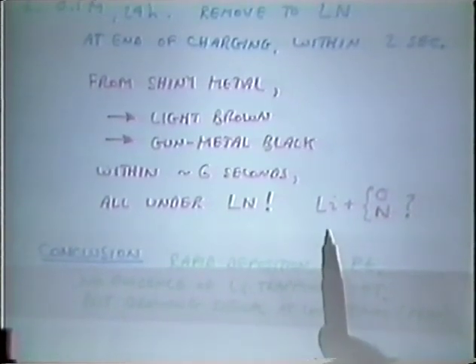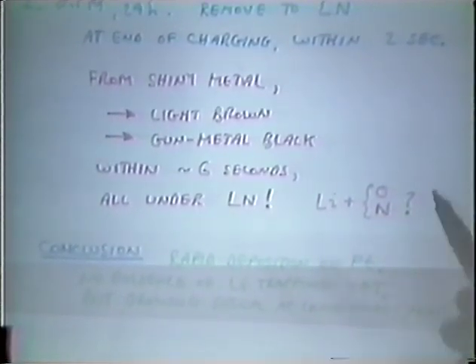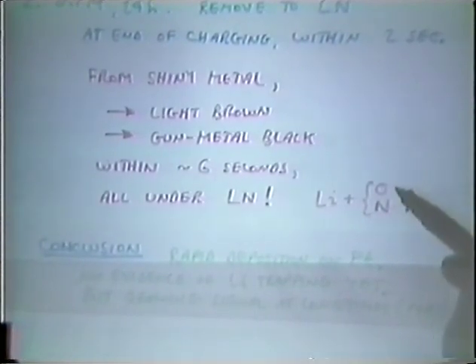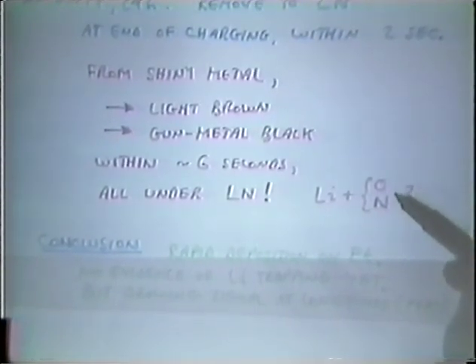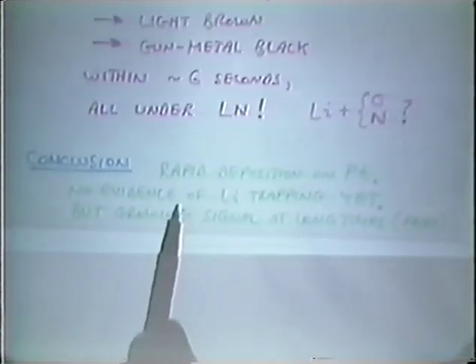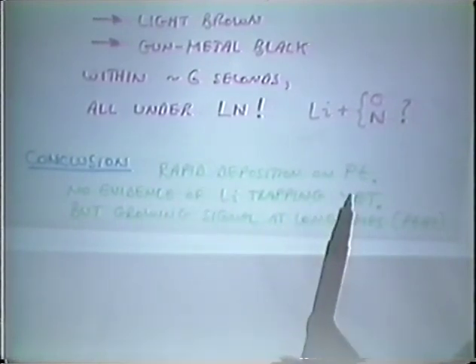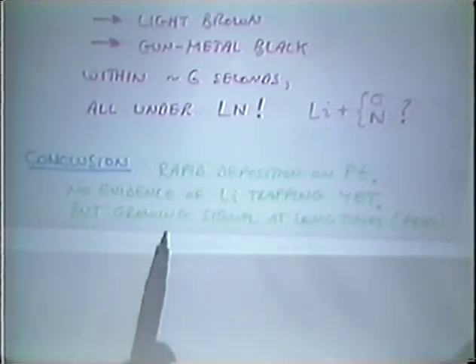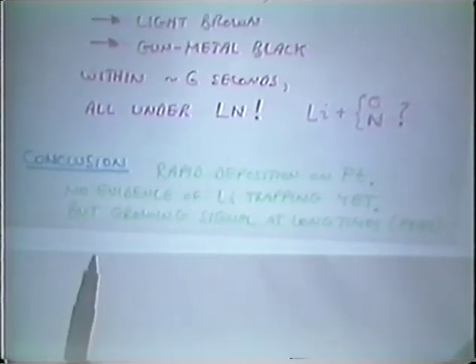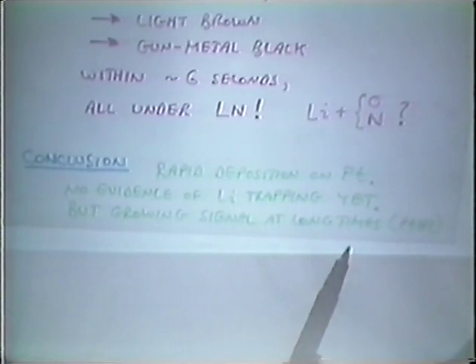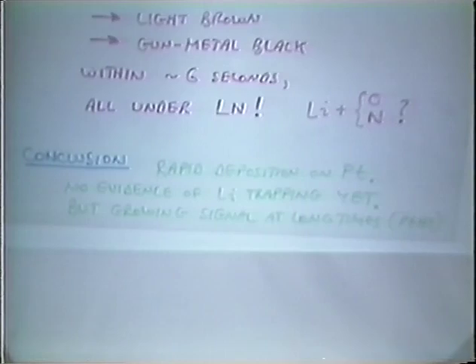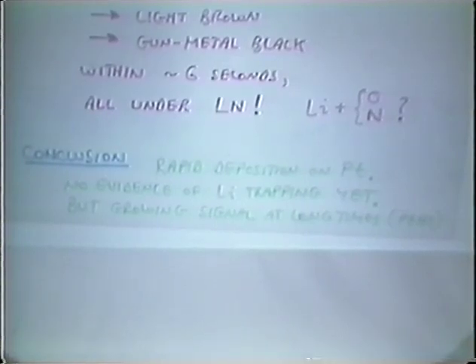Our hypothesis is that lithium had plated out, if you like, on the surface, had concentrated on the surface, and had either reacted with oxygen, which was dissolved in the nitrogen, or with nitrogen itself. Our conclusion is that lithium rapidly deposits on platinum. We have not seen any evidence of lithium trapping yet, although we're still looking, and we do see a growing signal at long times, which may be due to platinum hydride. As you may recall, yesterday Professor Bockris referred to the fact that lithium does plate out on platinum, so that's not perhaps unexpected.